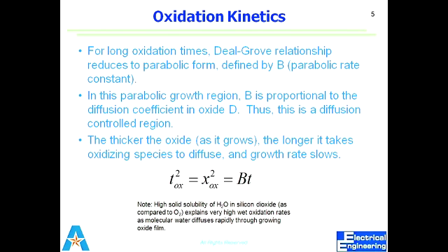So now you got the answer to your question, that when it gets thick there should be some problem. Now you come to know it is telling you yes, there is a problem. In this region, due to the thick oxide layer, the diffusion does not permit all the gas molecules to diffuse through, because it will offer some resistance. It will be reluctant to let all the gas molecules diffuse through it. So very few of the gas molecules reach the surface, and whatever reaches is getting reacted, because there are more silicon molecules as compared to whatever is reaching when the thick oxide layer comes into play.